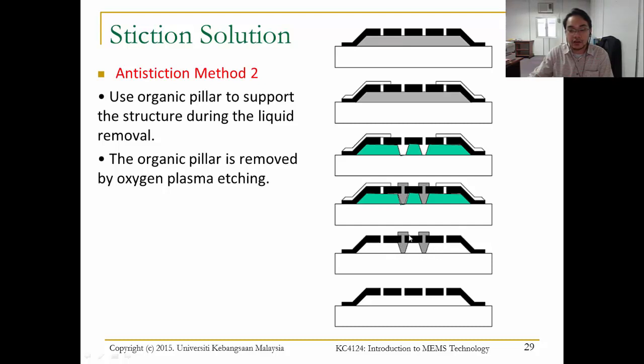By having this organic pillar, it will support the dome during the drying process. The organic pillar can be removed afterwards by oxygen plasma etching, which is a dry etching process, so there is no more problem with stiction.